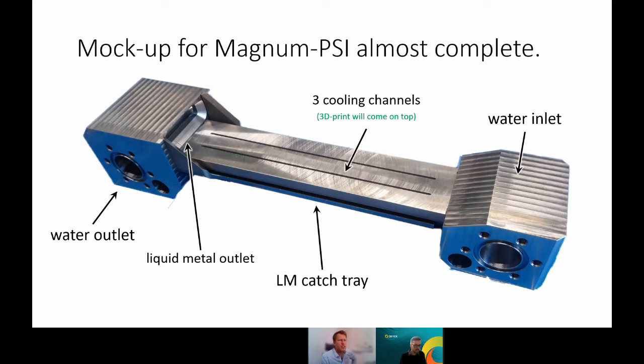Yeah, that's a good question. I think not actually, because the problem with cooling is usually not the total amount of heat, but it's the heat flux density, the amount of watts per square meter. And by radiating or somehow transporting to the first wall, which has a, you know, 1,000 times bigger surface area, you spread that out. And I think that that is definitely one way to go with this. Although I'm not an expert on the first wall and the constraints playing a role there, so I should note that, but I do think it's a good approach.